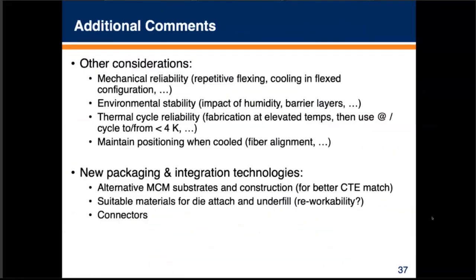So just some other considerations here. Certainly there's mechanical reliability. I mentioned a little bit about that, repetitive flexing, cooling and flex configurations, a lot of things to consider there. In terms of environmental stability, already talked about the barrier layers. There's also, in some cases, impact of humidity. Some of these structures were baked in a vacuum at 90 degrees C for 2 hours before we used them because polyimide can uptake water vapor.